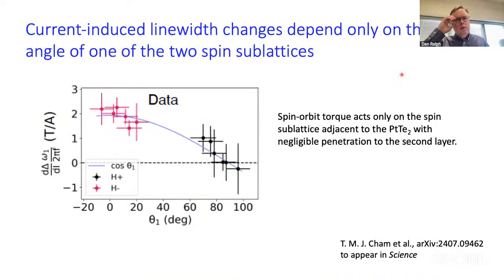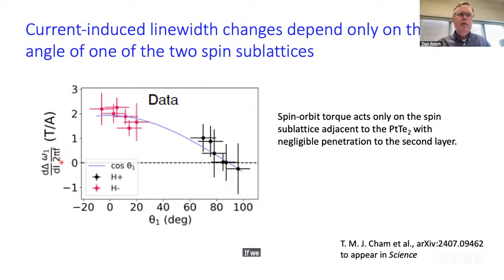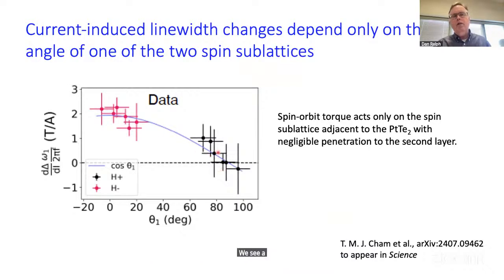Okay. So as a function of the magnitude of the magnetic field, you can vary the offset angle between the spin sublattices and actually check to what extent the angular dependence agrees with the simple pictures you expect from the ferromagnetism. If we do that, plotting the sensitivity of the line width to current as a function of the angle of that first spin sublattice relative to the current, we see a nice cosine theta dependence that is what you